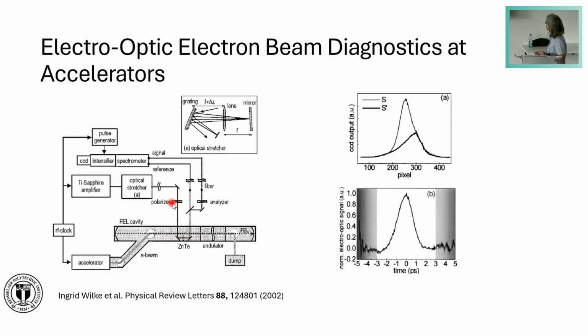The laser beam has a linear polarization, and afterwards the change in linear polarization is analyzed using an analyzer. This is the basic principle of the diagnostics. In this case, we did single shot measurements. The femtosecond laser pulses were stretched with an optical stretcher, so that the laser pulse was slightly longer than the electron bunch. Then, if we capture the single laser pulses, we have the full information on the electron bunch length.